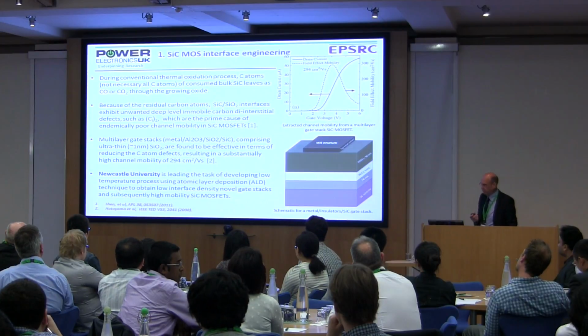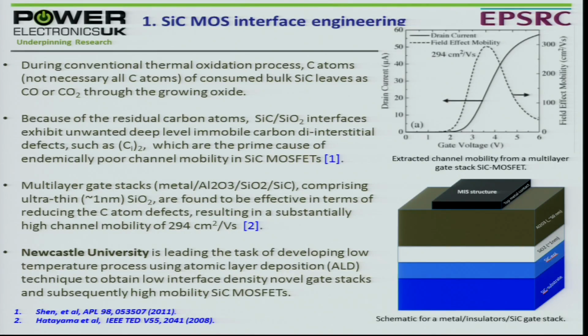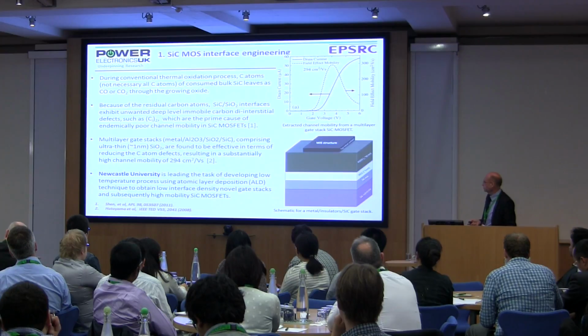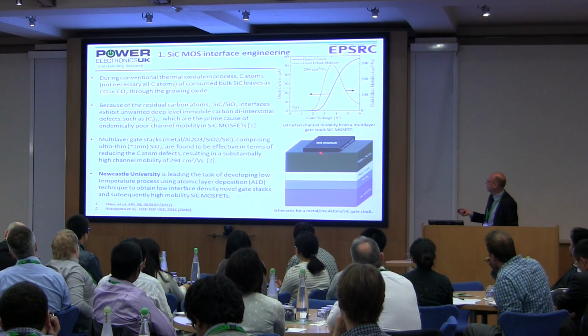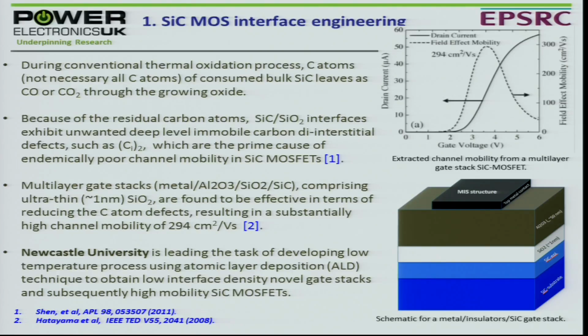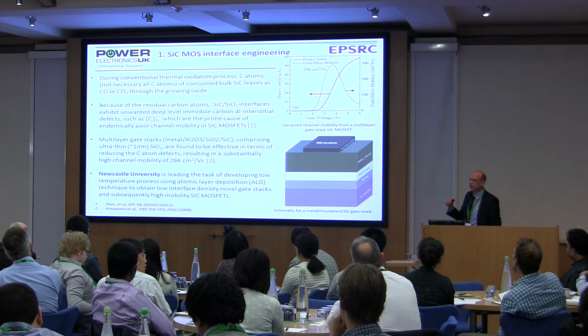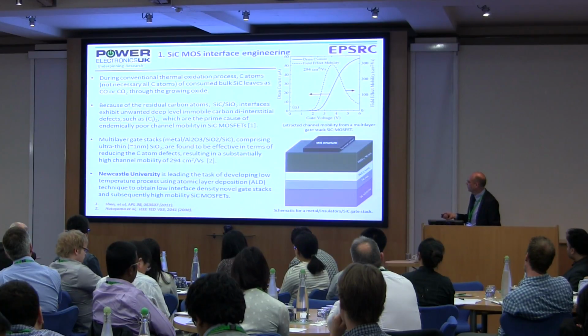So, what have they been doing? Again, they've been looking at trying to improve this oxide interface. But in the previous example that I showed you, there was actually thermally grown oxide. Here, what they're trying to do is to use different materials for the gate oxide. So it's not MOS, it's metal insulator semiconductor. And they've been trying to use alumina on top of a very thin layer of silicon dioxide. So you have an extremely thin, just a few nanometers of normal silicon dioxide, and on top of that you put an ALD deposited